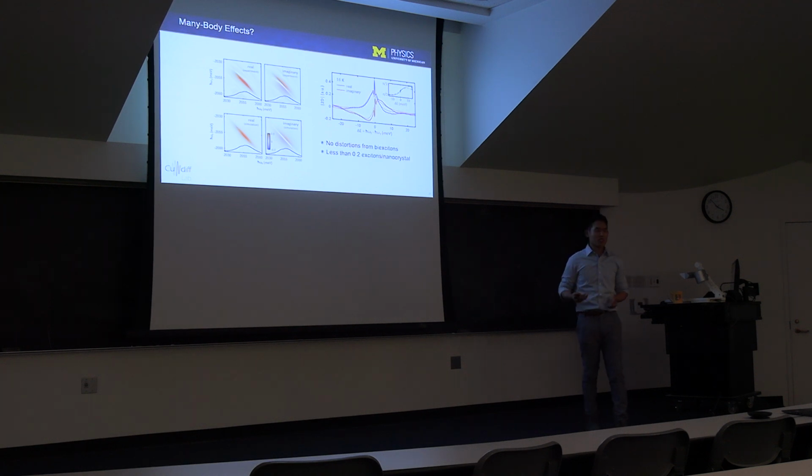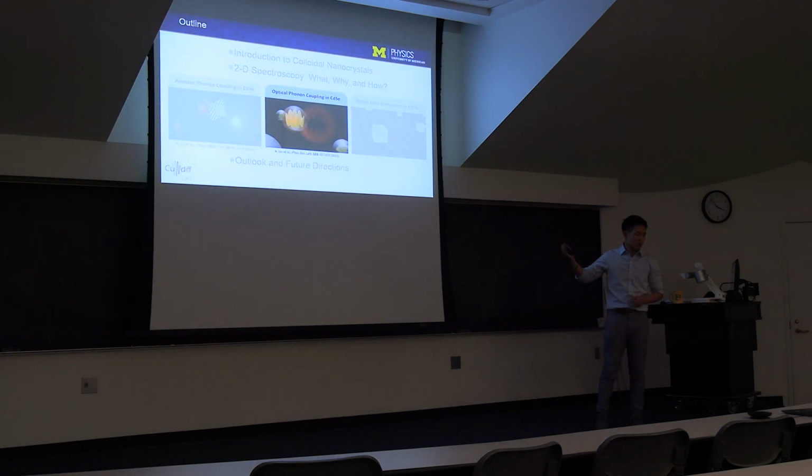And accumulation effects should also not be an issue, since from our calculations, at our excitation densities we're exciting less than 0.2 exciton per nanocrystal. So that was the end.